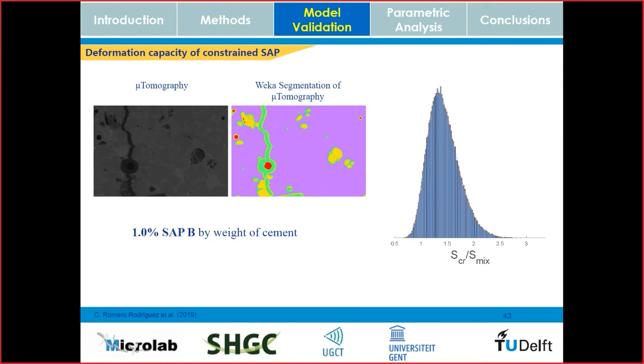So we had to measure this, which is the absorption capacity of the superabsorbent polymers in the crack, because they are also constrained by the crack walls, and there are a lot of forces in play here, not only osmosis, but you also have mechanical forces that counteract this swelling of the superabsorbent polymers. So what we did, we kind of drew inspiration from Hong and Choi, and then we did a CT scan of a saturated sample with superabsorbent polymers, the ones that we were studying, specifically the ones that Snoeck used, and we showed the results as well for the sound samples.